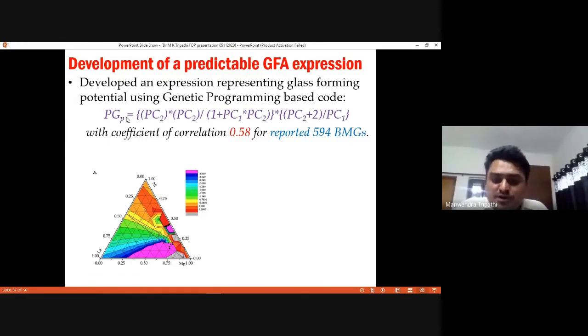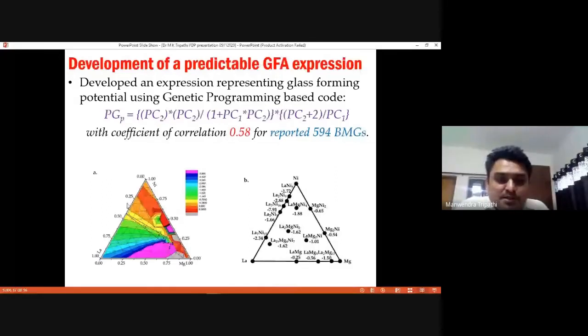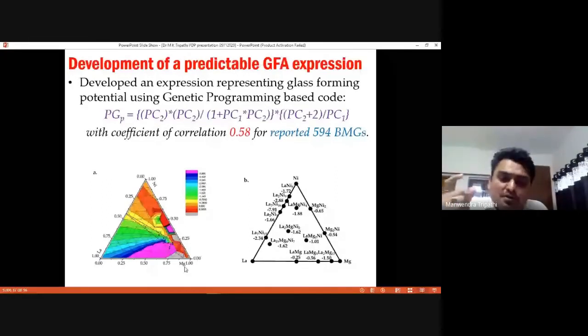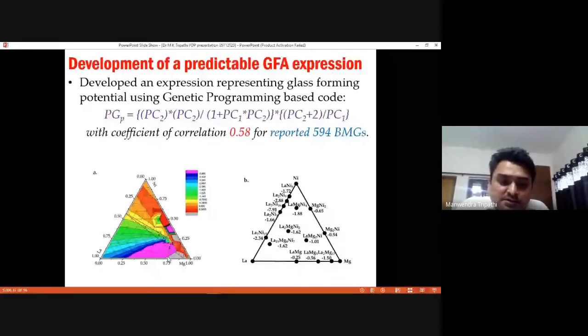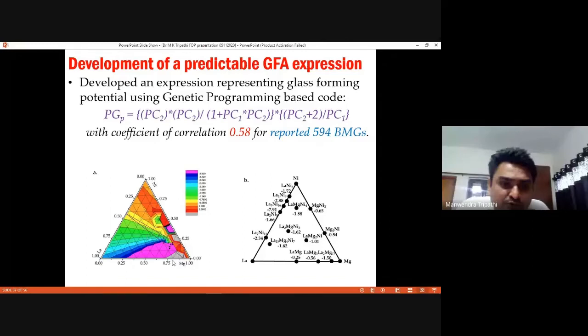So what we have done is that we have taken a 3-component system, lanthanum, nickel, and magnesium based system, where the metallic glasses are formed, right? And we are plotting the PGP here. So various colors you can see here, right? And inside this plot, you can see another triangle, right? So here, I have chosen eutectic compositions. The eutectic of nickel and lanthanum falls over here. Eutectic of nickel and magnesium falls over here. And eutectic of lanthanum and magnesium falls over here. So if you join them, this is an artificial triangle we are deliberately putting over here.